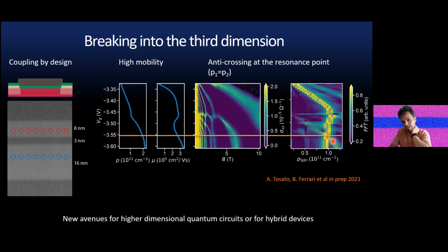And if you do electrostatic modeling of the whole system, you really can reproduce these kinds of curves. Also interesting here, you see an effect on the first quantum well, with the density actually decreasing. And this is an effect due to a correlation between the two layers. It's a commensurability effect. So the question also is, what will we do with these quantum wells? There are a lot of options we can think of, actually moving into the third dimension for quantum circuits or even for hybrid devices.